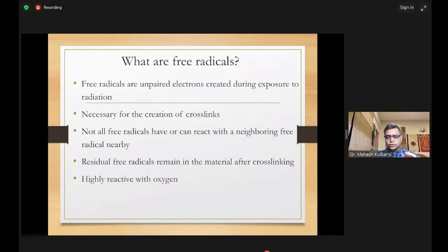So once you subject that ultra-high molecular weight polythene to either gamma or electron beam irradiation, you get cross-linking, but at the same time, you create some free radicals. So what are these free radicals? These are unpaired electrons which were created during exposure to radiation. They were necessary for creation of cross-links, but not all free radicals can react with a neighboring free radical, and some of them are left as residual free radicals in the material itself.